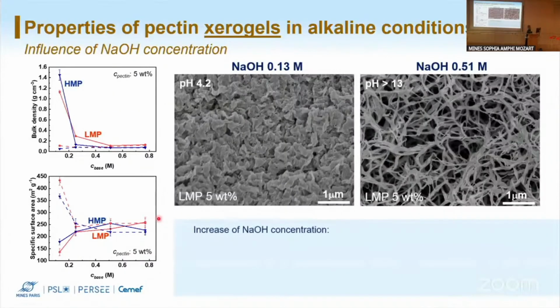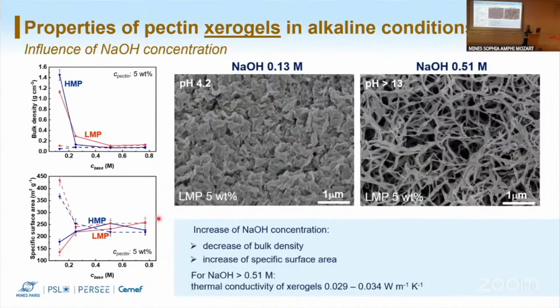So for the xerogel materials, when we increase the concentration of sodium hydroxide, we have a decrease of bulk density. We have an increase in specific surface area, and we tested the thermal conductivity of the materials that showed the best surface area and bulk density values, and we saw that it was between 0.03 and 0.035 watt per meter Kelvin, which is not super insulating, but is very low still. It's in the level of the insulation materials that are used right now.